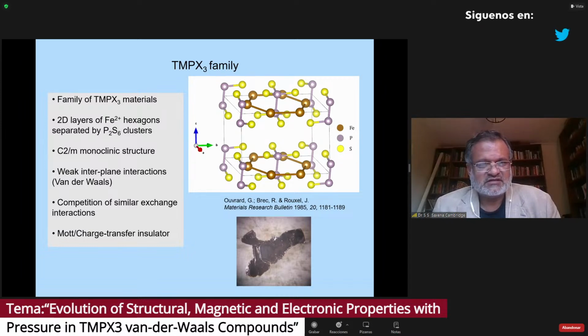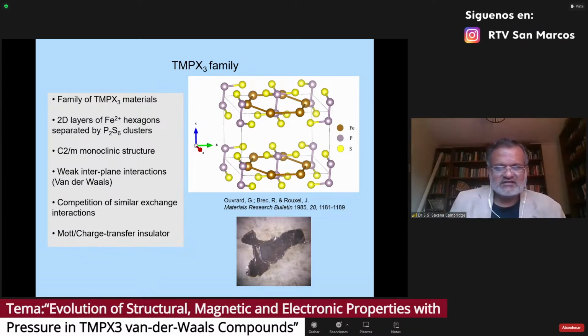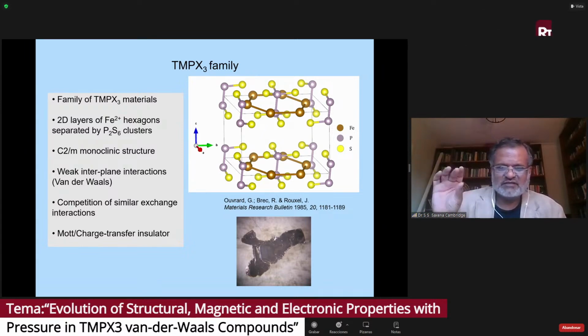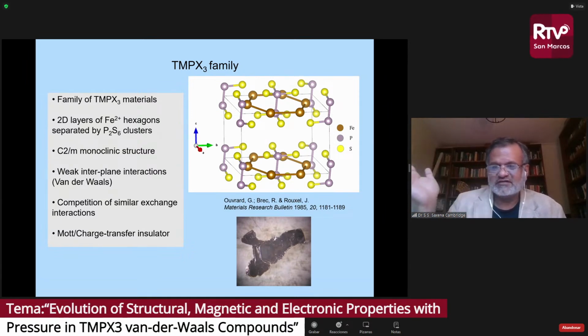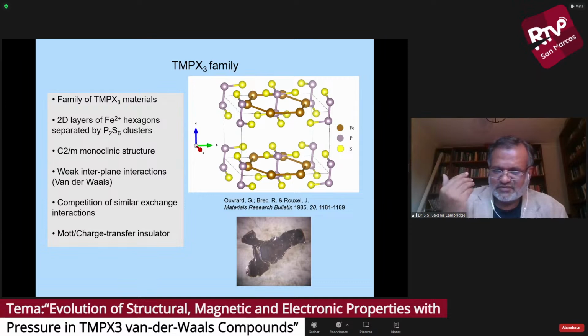But these are generally 2D layers of iron 2 hexagons separated by P2S6 clusters. Generally they have this kind of monoclinic structure, and they have weak inter-plane van der Waals interactions. In fact, they can be peeled just like graphite into single layers of graphene. Most of them are Mott insulators. So they fitted our requirements quite well in many ways.